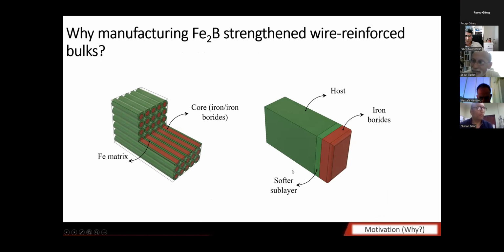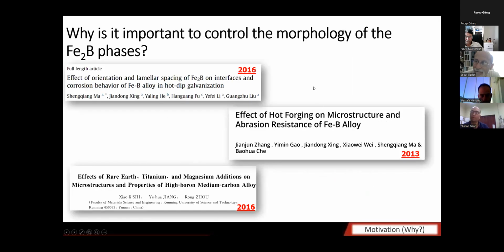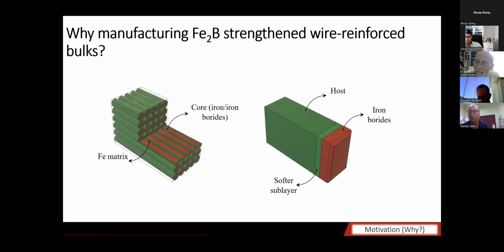What was your aim? Well, first of all, as I showed you here, they have been using these different methods to control the morphology of iron borides. And the main purpose of using the iron borides was to control the corrosion behavior, and also to make a material which is corrosion and wear resistant, using a quite difficult manufacturing approach. My main focus was to use an easier and much less complex manufacturing approach, but eventually, because the phases which are produced are very hard and tough at the same time, they are most suitable for wear and tribological applications.